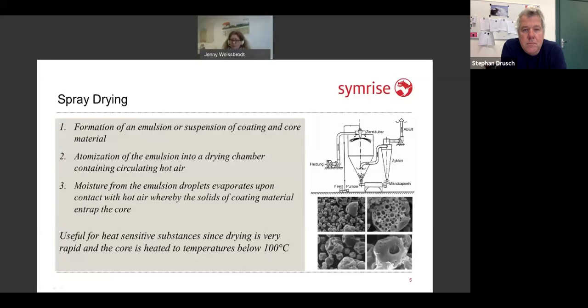This is a very energy-consuming process, and this is why the temperature never exceeds 100 degrees C. Only you are in the range of 80 to 90 degrees C. So out of this process, you get comparatively small particles of, let's say, in lab scale 10 microns, up to 100 microns in an industrial scale.